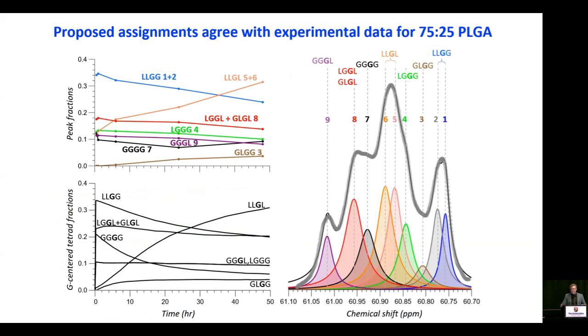And so these are the tetrad assignments to each contribution to the glycolide-centered methylene. The experimental data there is in the upper left, and the stochastic model prediction there is in the lower left. And so you can see that there's essentially a one-to-one comparison now.